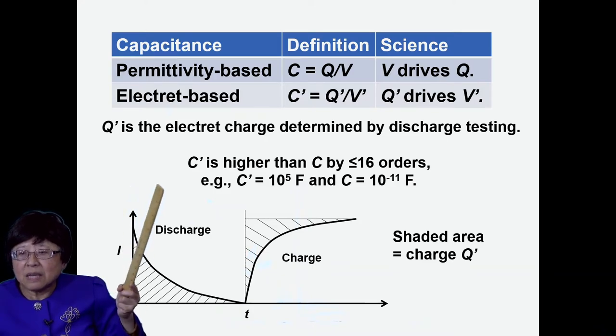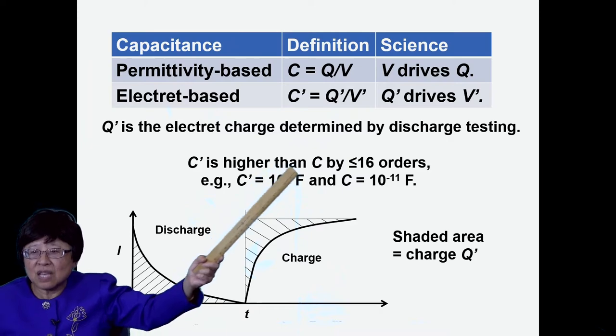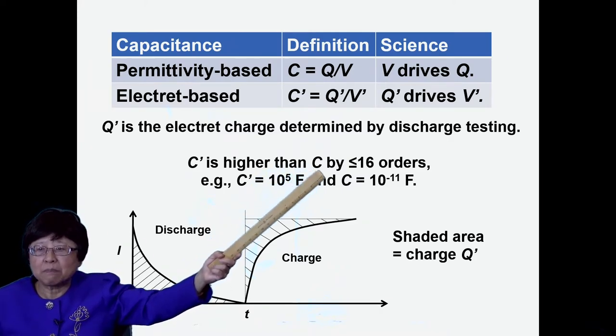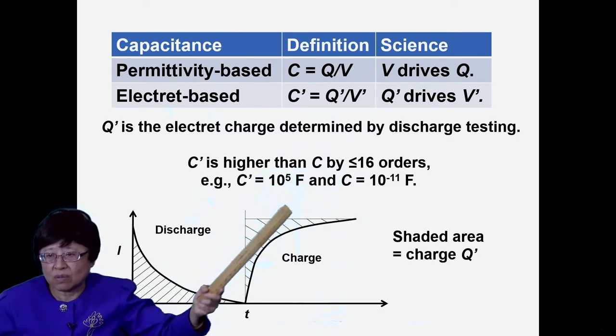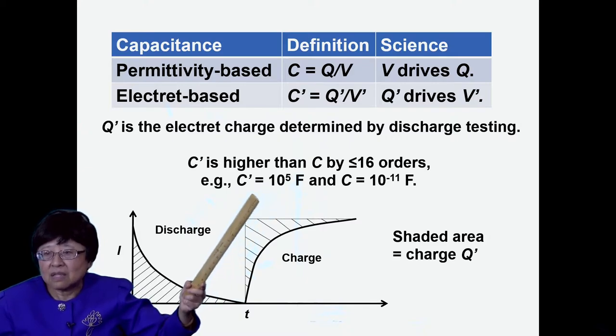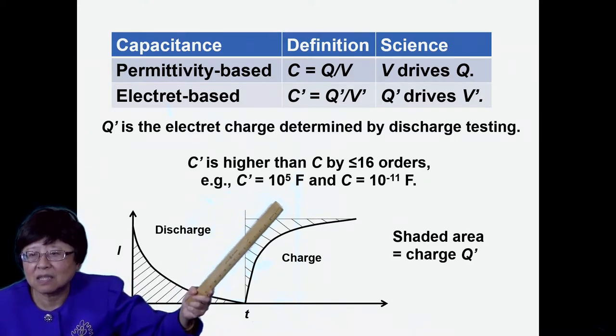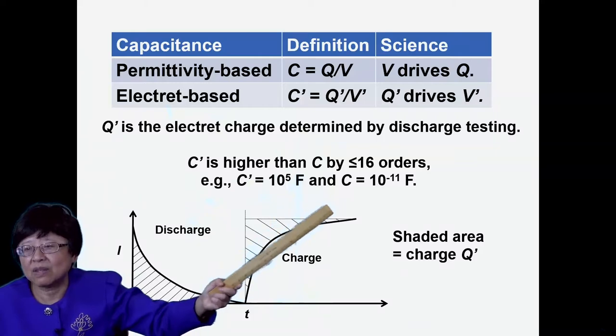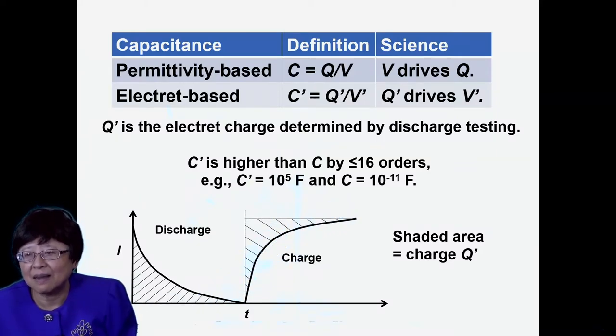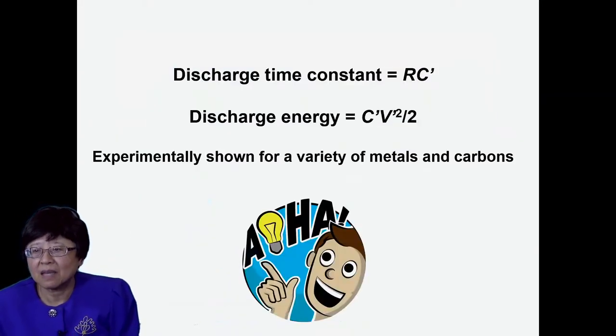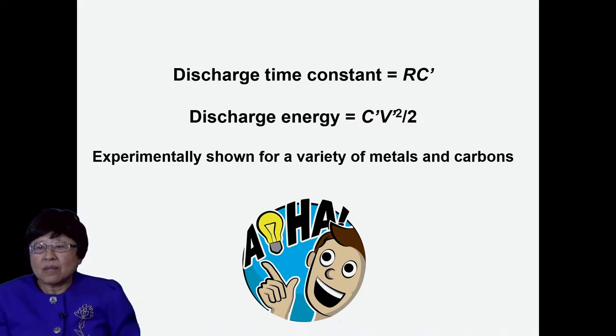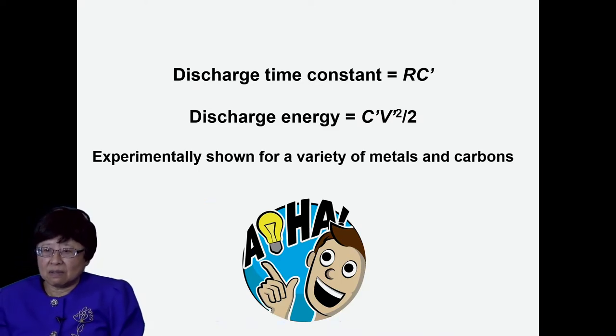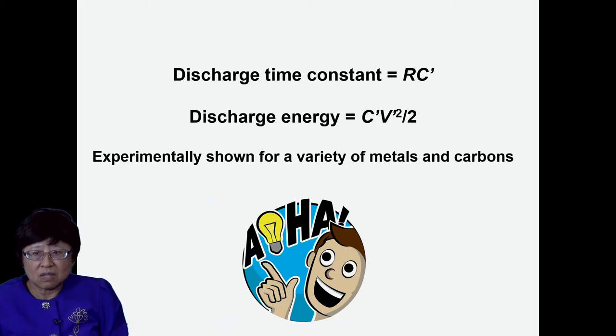It turns out that C prime, the electret-based capacitance, is higher than C, the permittivity-based capacitance, by up to 16 orders of magnitude. C prime can be, say, 10 to the 5 farads, with C being only 10 to the minus 11 farad. So the discharge time constant for this electret discharge is RC prime.